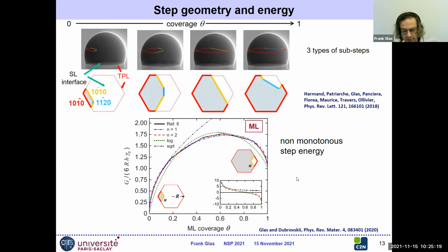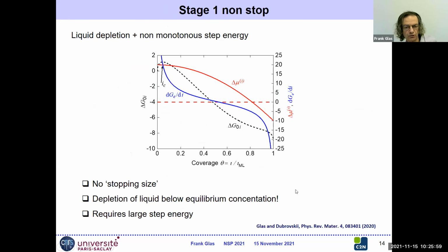And it's important because you remember we're interested not mainly in the step energy, but in the derivative of the step energy. So here is the derivative which is plotted. The curve in black is the standard curve without taking into account this non-monotony. So the derivative is infinite at the beginning and then slowly goes to 0, as the inverse of a square root. But if it's non-monotonous, it's also plus infinity at small coverages, but then the derivative goes to 0 at some size, and then it goes to minus infinity for large coverages. So that's really important. So how can we take it into account?